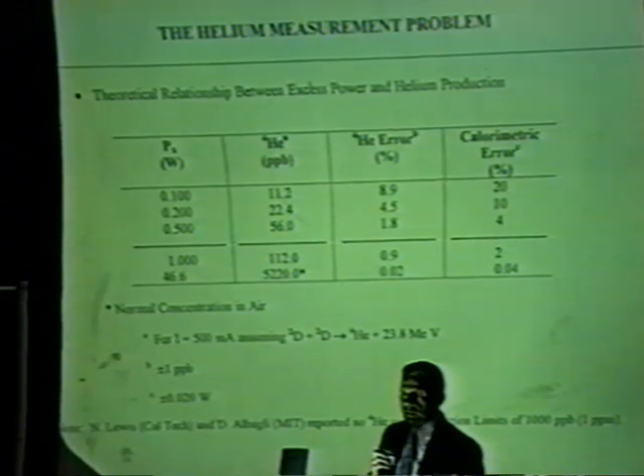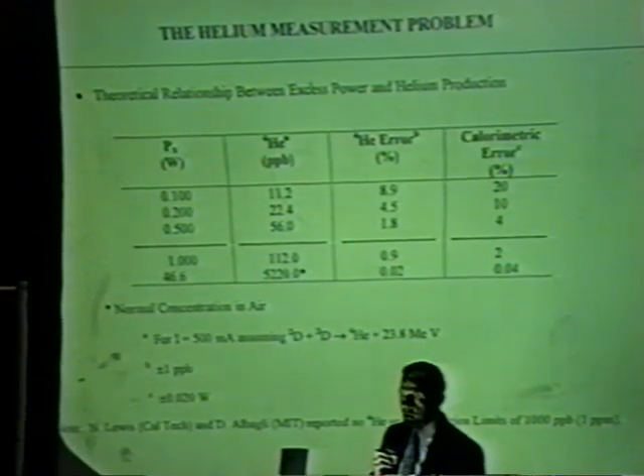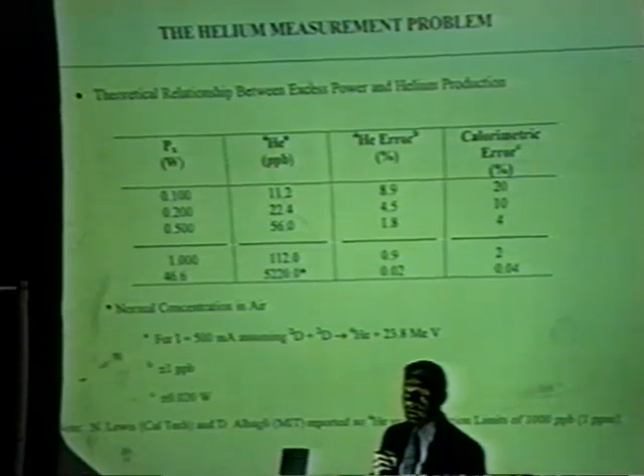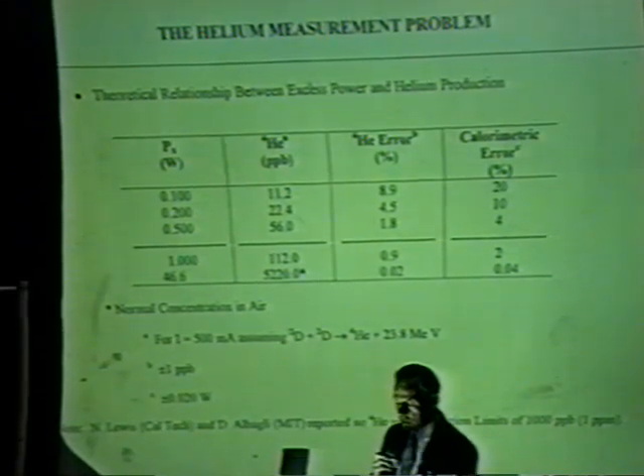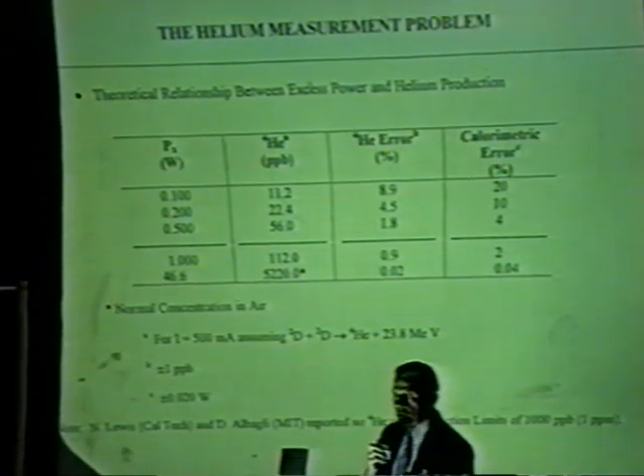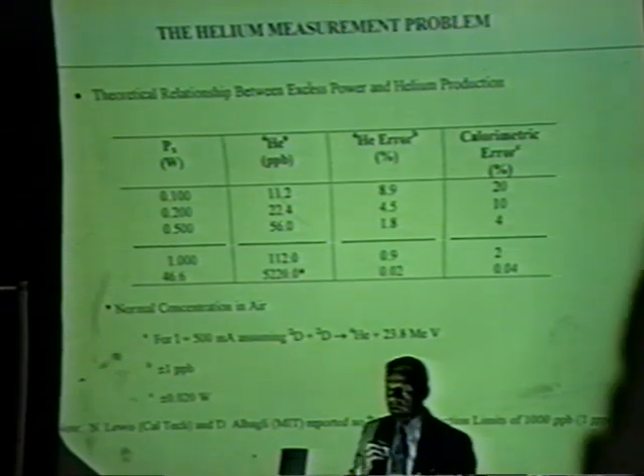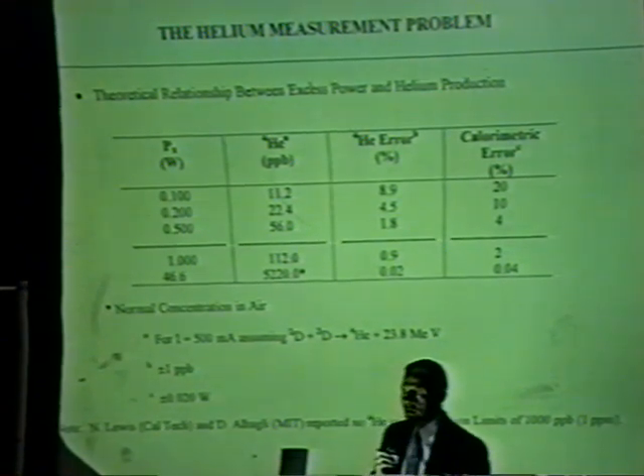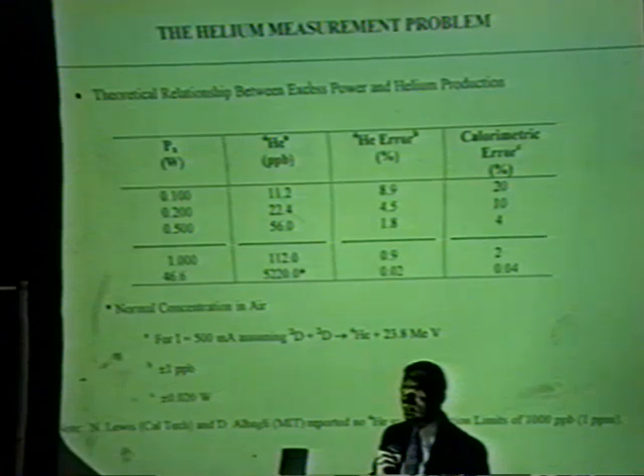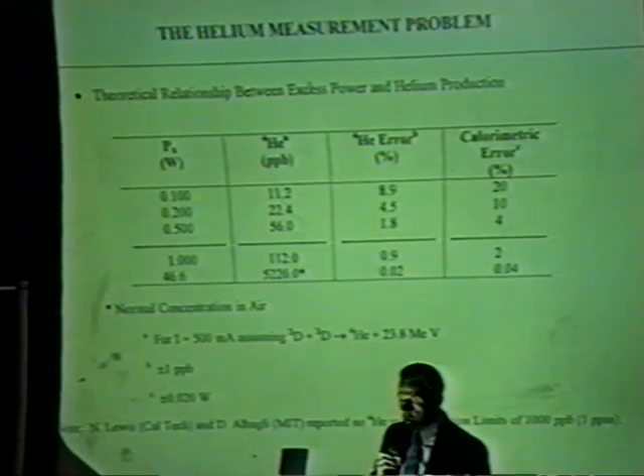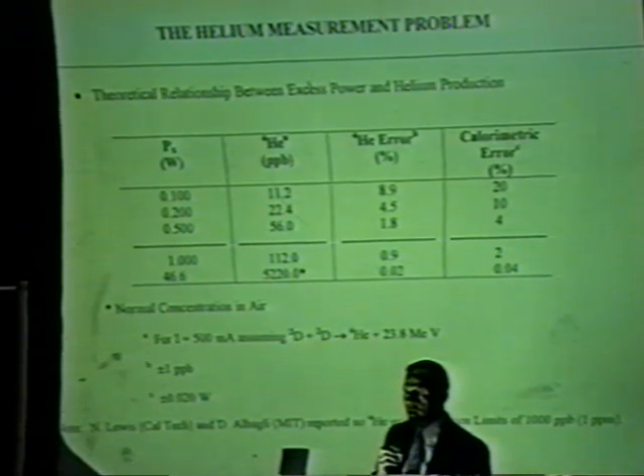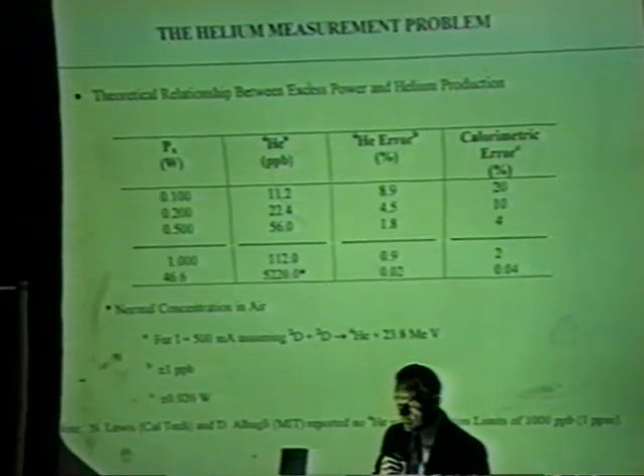So people that say, we'll believe you if you can get more helium than in the atmosphere, it's almost impossible, because before I get even to 10 watts, in all the calorimetric systems I've used, it would boil away. So you would not even be able to get to that point, equaling the concentration in air. So you have to really work on control experiments to show no excess power, and see what your background helium is in that case, and compare with cases where you have excess power.